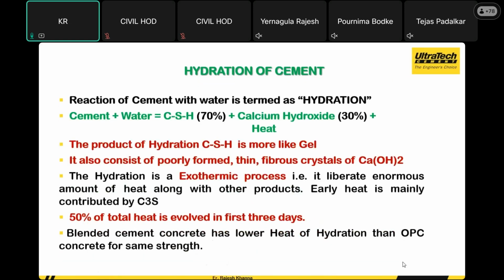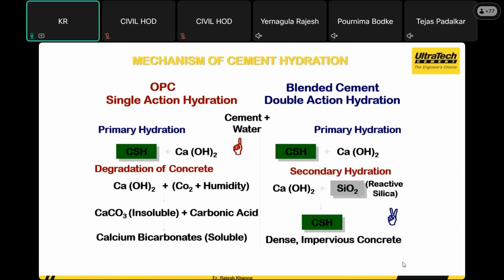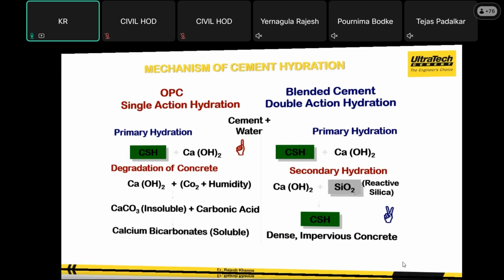When we see hydration, how this happens when we add water to cement or to any concrete, we have a reaction which forms C-S-H gel, which is more like a gel. So calcium hydroxide of 30% plus heat, and we will have a double reaction, to make you understand. With an OPC grade of cement or concrete, you will have only single action hydration. Calcium hydroxide plus CO2 plus humidity would degrade, and there would be only single action of hydration. Blended cement will have a double action hydration, where the leftover calcium hydroxide will also react with the reactive silica, to give a denser impervious concrete. It means all the packing system is done in such a way.